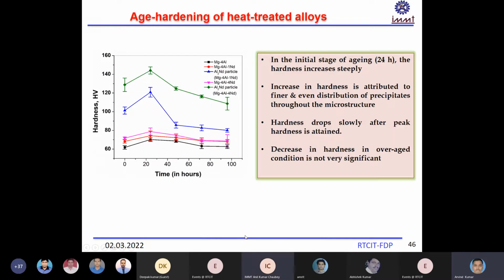So here you can see this aging graph, and the hardness was taken at different aging times. This is the 24 hours time. After 24 hours, again the hardness is decreasing drastically and then becomes saturated. From the microstructure, it is also showing that when you go above 24 hours, your particle size becomes